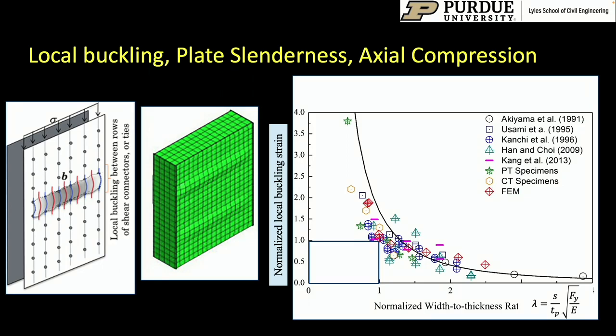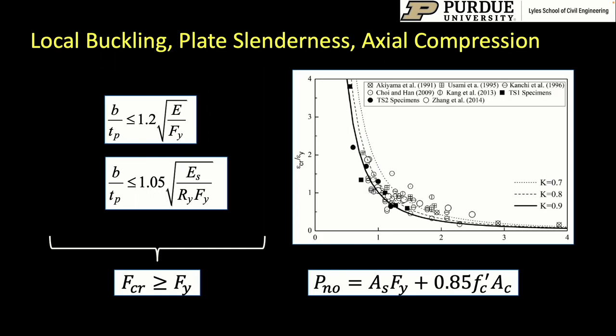We took all this experimental data and combined it with our own numerical finite element analysis and test data in order to look at what was causing the local buckling of the steel plates and what would it take to modify the slenderness of the steel plates so that it would yield first and then undergo local buckling in compression. We were able to compile all of this experimental and numerical data and develop a simple recommendation for the slenderness requirement for the steel plates in the post-concrete cast and hardening phase. These requirements, if met, will give you a steel plate that is going to be non-slender, which means that it will undergo yielding before it undergoes local buckling.